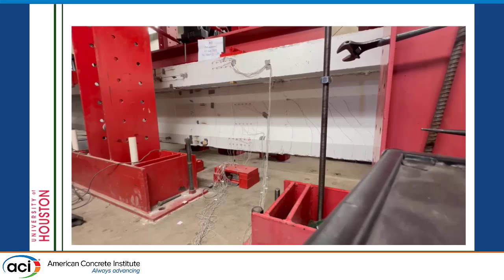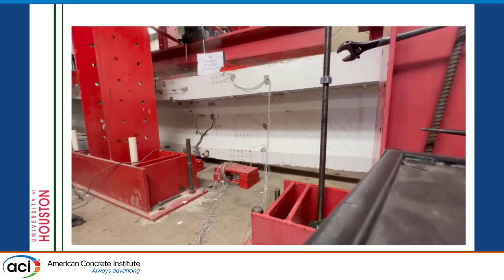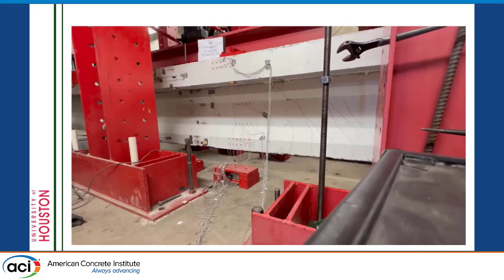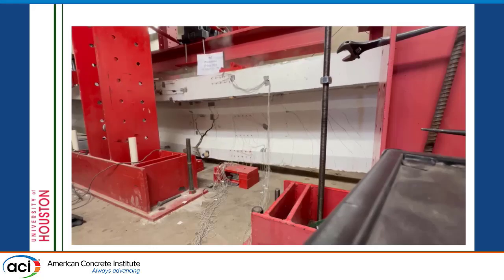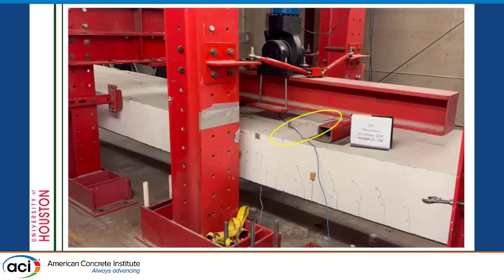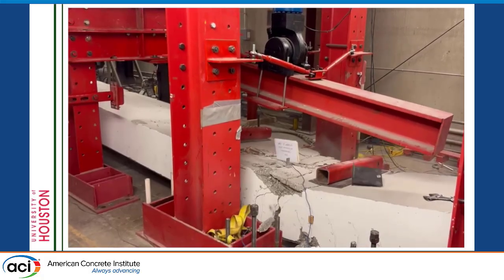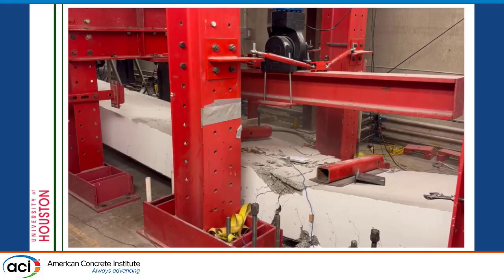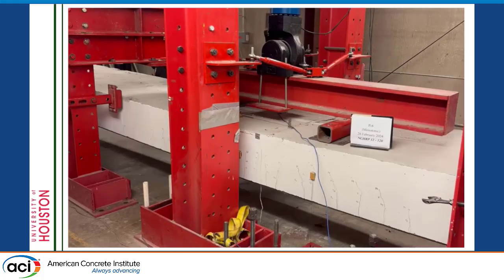Here we didn't reach the maximum concrete strain on the top. And our goal is to have this strand rupture because concrete crushing is the same. This is the balance condition. It was a little bit hard to get this one, so we tried to get them at the same time, and you can see on the top it's concrete crushing, and after that we got strand rupture. So we wanted to get all the cases that we have: strand rupture, balance conditions, and concrete crushing.